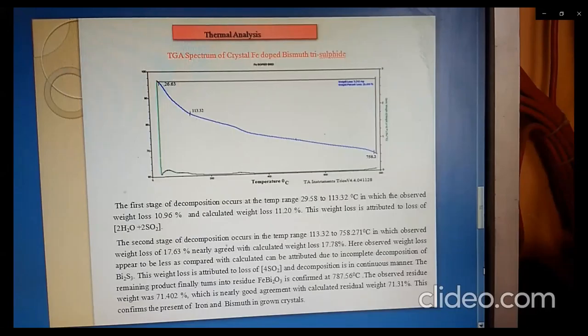FeBiO3 is confirmed at temperature 787.56 degrees Celsius. The observed residue weight was 71.402%, which is in good agreement with the calculated residual weight of 71.31%. This confirms the presence of iron and bismuth in the grown crystals. These are the conclusions.